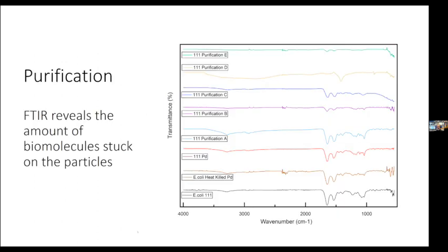Last but not least, we have taken first steps to show that we can actually purify these nanoparticle materials from the bacterial cells for potential industrial uses. This shows very preliminary experiments with different purification protocols. What this is is Fourier transform infrared spectra that show the presence or absence of biomaterials still stuck to the particulate material. You can see that purification protocol E on top has almost no organic material left on the particles, while some of the other protocols still have significant amounts of organic materials stuck to the particles. At the bottom are the control samples that have not been treated.